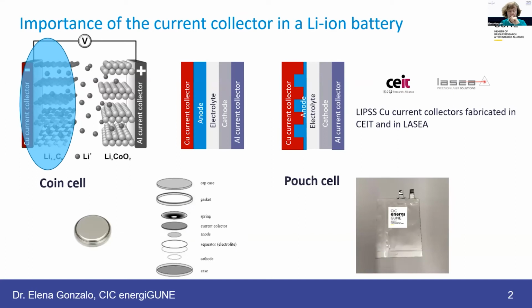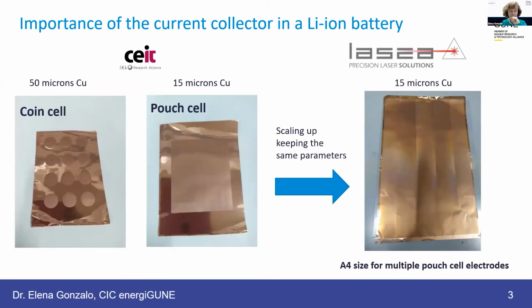We have tested these current collectors in two different devices, not only in coin cells, but also in pouch cells. That was the objective, the goal of the project. Try these current collectors in a monolayer pouch cell as our demonstrator. As you can see from the left-hand side to the right-hand side of the slide, firstly, Ceit fabricated coin cell shapes of the nanostructured areas in the 50 microns copper current collectors. We were testing all the different parameters they were playing with, and finally we got the best ones for our electrochemical response. Those parameters were transferred by Ceit to pouch cell size with thinner copper current collectors, and at the end of the project it was scaled up by Lasea, keeping all the same parameters that were useful for us, in this A4 size shape for multiple pouch cell electrodes.